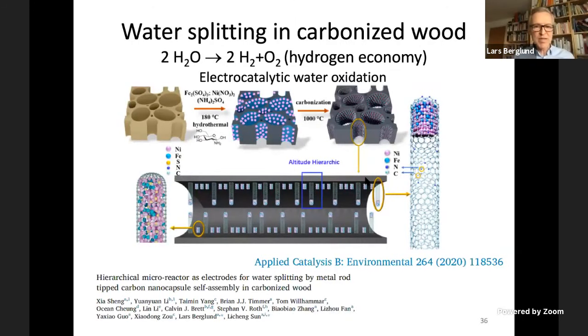And the final example is water splitting. This is Junjun's collaboration project with Licheng Sun. So I think we're getting somewhere here compared with charcoal used in our barbecue. Basically what they're doing is that they carbonize wood in a very controlled manner, and they want to utilize the microfluidic character of the lumen channels. Then they functionalize this with catalytic particles, and they grow entities here from the lumen that can provide catalysis.